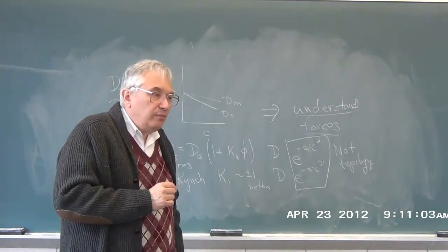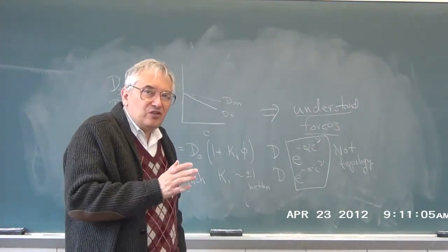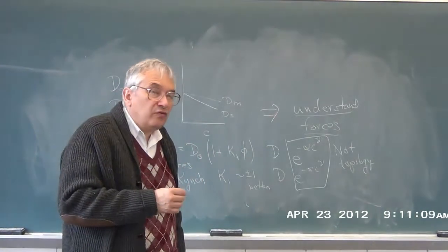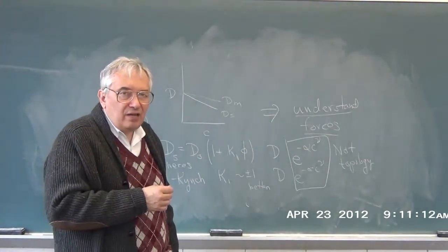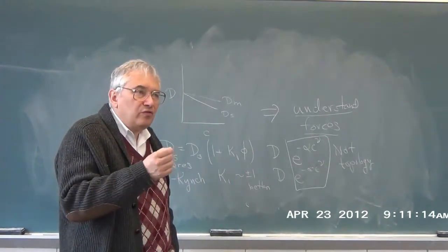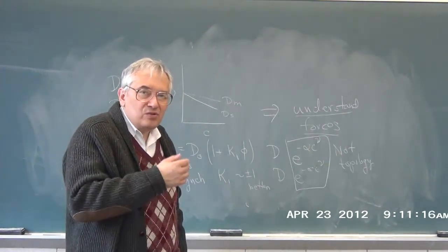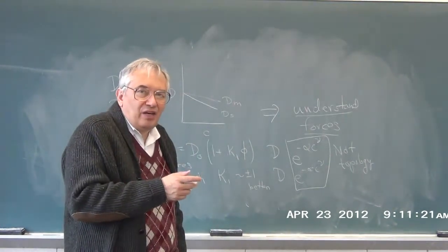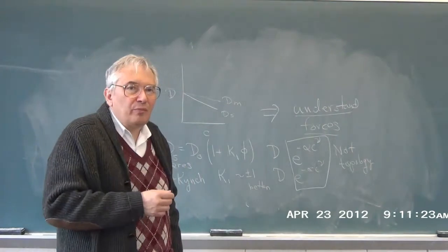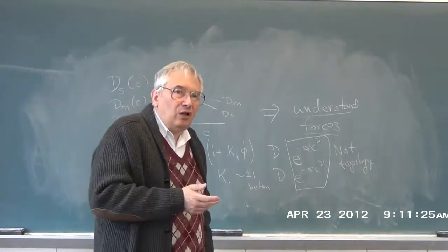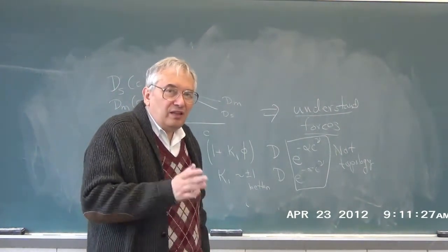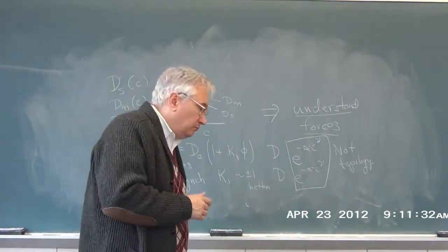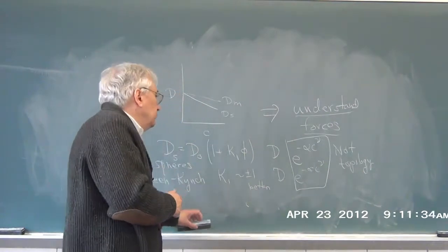For example, spheres have this phase transition starting at volume fraction 1/2 going up to volume fraction 0.58, and then at about volume fraction 0.72, slightly less than 3/4 by volume. They're close packed, you can't fit any more. Polymers will form melt in which more or less all of space is filled by polymers, and that actually is a geometric packing issue.